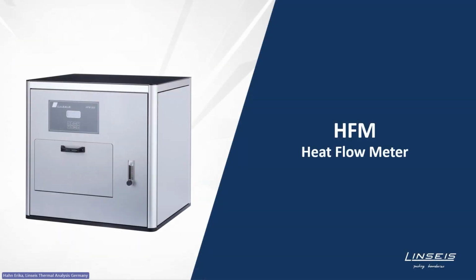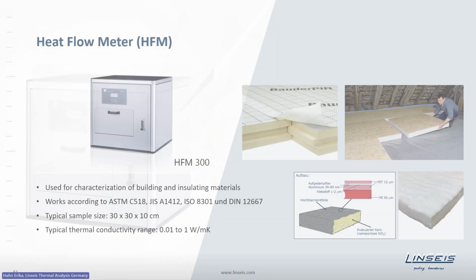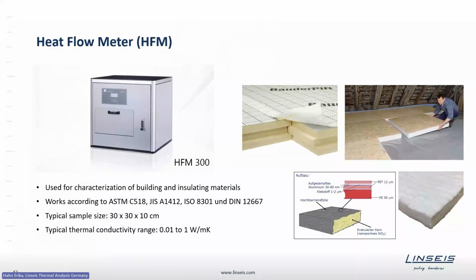Coming now to the last instrument we will have a more detailed look at: the heat flow meter, the steady state measuring method, also based on this plate method. The heat flow meter is especially useful for insulation materials, so materials with a conductivity lower than 1 or even 0.1 watt per meter Kelvin. So mostly this tool is for insulation materials, building materials, and so on. It's also a standardized measuring method.